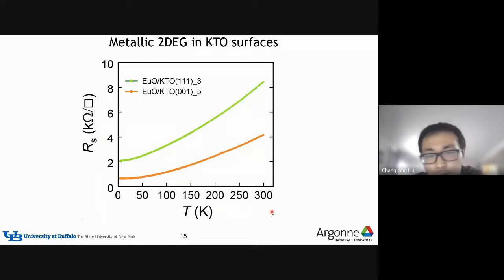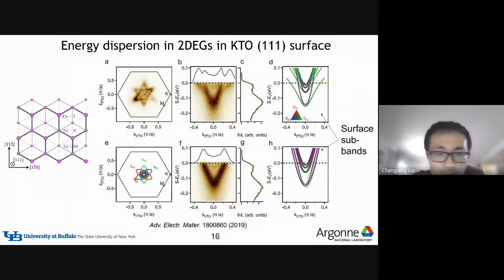So here I'm showing you the measurement of the EuO KTO interface. The measurement is basically performed from room temperature, 300 K, to about 4 Kelvin. In both of these samples, the green color represents the measurement on sample EuO KTO 111. So I emphasize the KTO 111 interface. It shows a metallic behavior with resistivity, or sheet resistance, decreasing as temperature is lowered. And for EuO KTO 001, it also shows a metallic behavior.